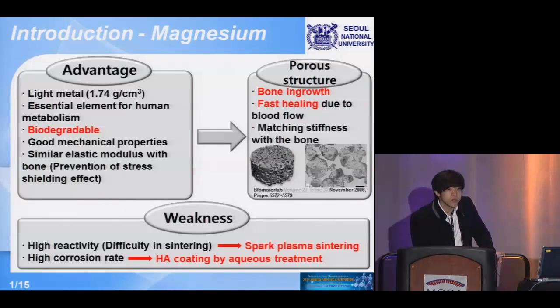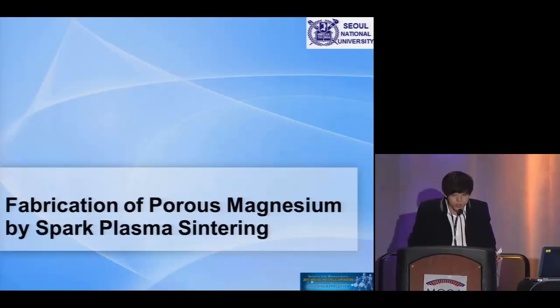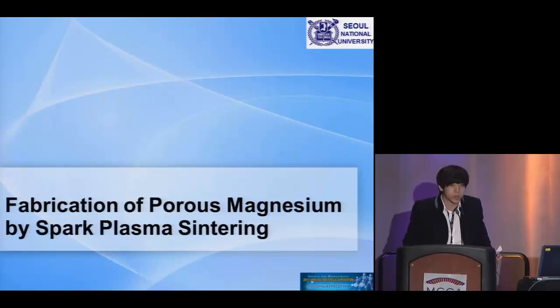So to solve these problems, we use spark plasma sintering to sinter porous magnesium, and we coated this porous magnesium with hydroxyapatite by the aqueous treatment to improve the corrosion resistance and biocompatibility. I divided it into two parts. First, the fabrication of porous magnesium, and second, the hydroxyapatite coating part. The first one is the fabrication of porous magnesium by spark plasma sintering.